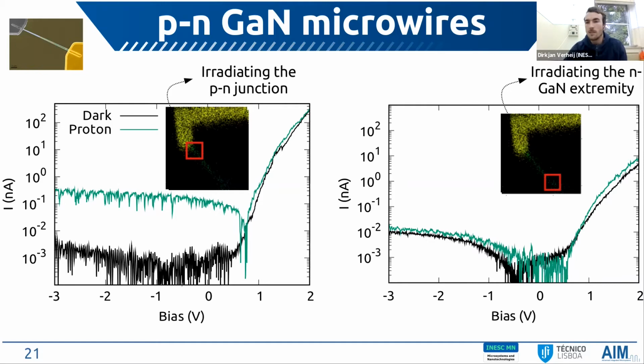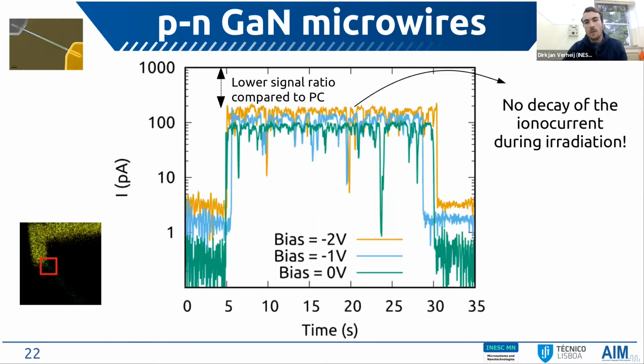This means that it is really the depletion region created by the p-n junction which is responsible for the creation of the ionocurrent signal, and that the n gallium nitride part has a low influence on the signal. Then, moving on to the transient measurements while irradiating the p-n junction again, we saw, and this is maybe the most surprising result, that there wasn't any decay of the ionocurrent during the irradiation. When irradiating for 25 seconds, the ionocurrent actually maintains a stable value, and we see no decay at all, which was obviously not the case for the n-type microwires.